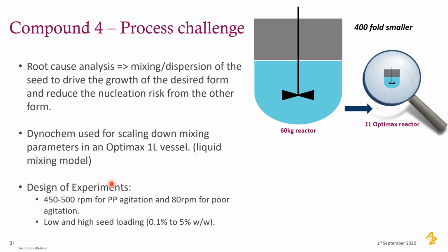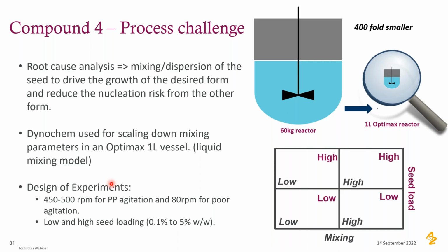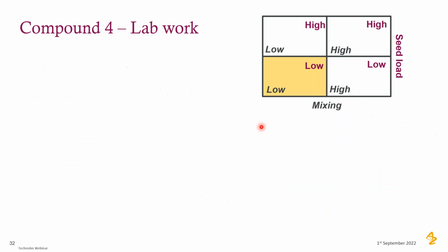And what we did is we did a design of experiments. So we decided to do high mixing and low mixing, by changing the agitation speed, and we decided to do low seed loading and high seed loading. And we came up with that small design of experiments of 4 experiments, changing only the seed and the mixing. And that was the only thing we could actually change for that next batch. So we decided to focus on what we can control and do.